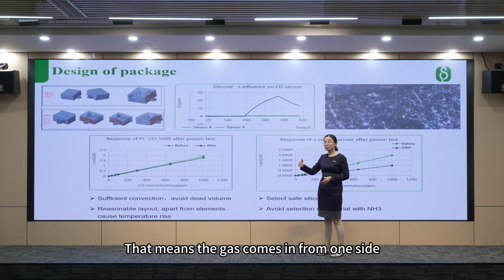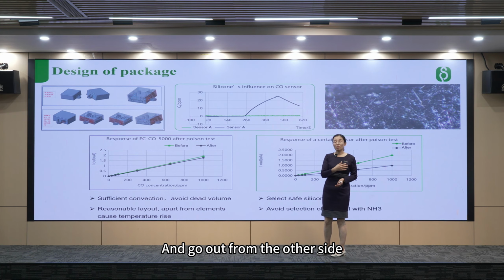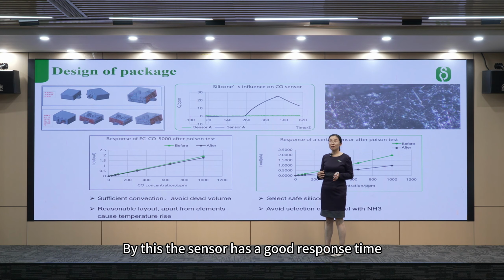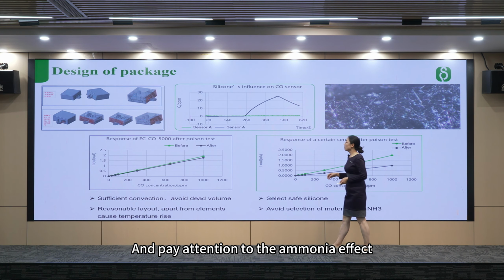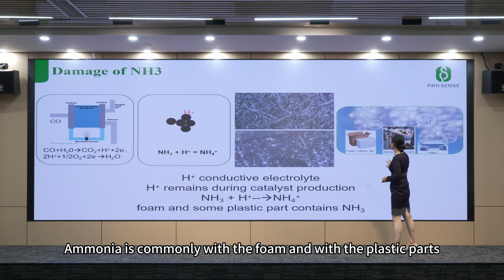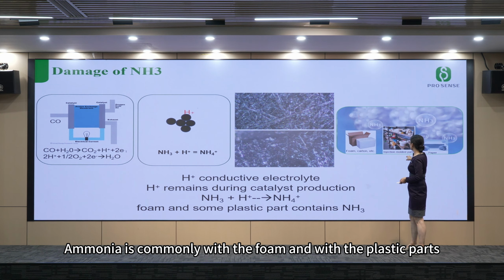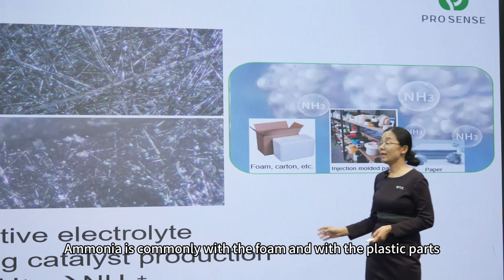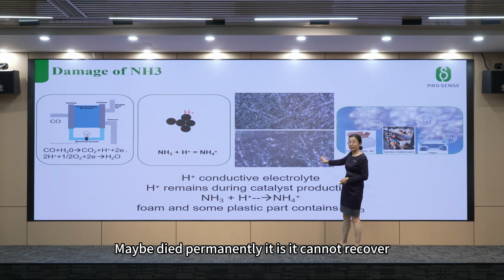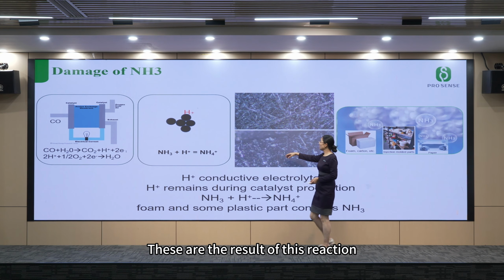That means the gas comes in from one side and goes out from the other side. By this, the sensor has a good response time. And pay attention to the ammonia effect. Ammonia is commonly found in foam and plastic parts. The ammonia will react with the acid part in the sensor, which will cause the sensor to be damaged, maybe die permanently. It cannot recover.